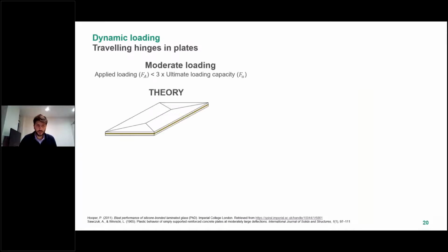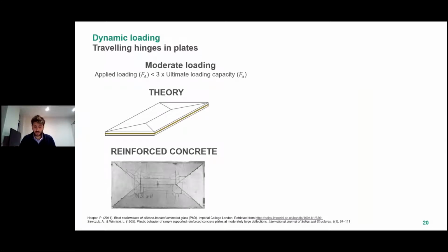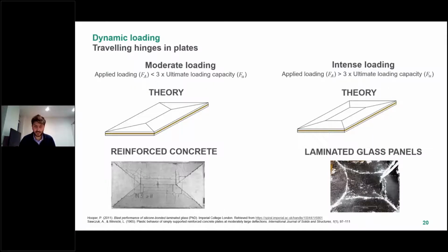These conclusions from the one-way spanning beam specimens are very important, as when these are extended to 2-way spanning plates, it can explain why we observed a different yield line pattern in reinforced concrete when a uniform static load pressure is applied, compared to laminated glass when a dynamic short duration intense magnitude loading is applied to the entire panel. And this is why we see a different yield line pattern.